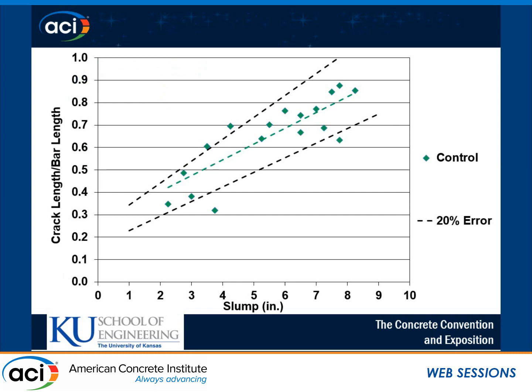Here's an example of one of our control series. For each of these graphs, we have slump on the x-axis and the ratio of crack length to bar length on the y-axis. So if each one of our specimens in a single mixture had a crack 12 inches long over the entire length of the bar, that ratio would be 1.0. I also want to point out that each data point here is the average of 3 specimens that we do per mixture. And it's important, because we do get a lot of scatter with these series, that we make sure we do enough mixtures in order to make sure we're getting a good trend line out of that.